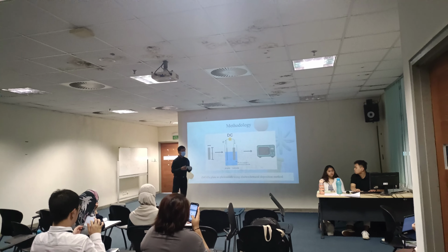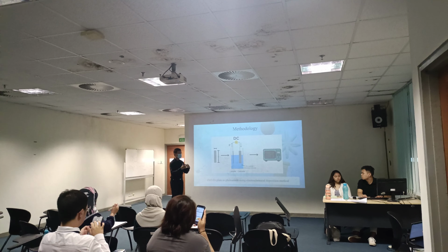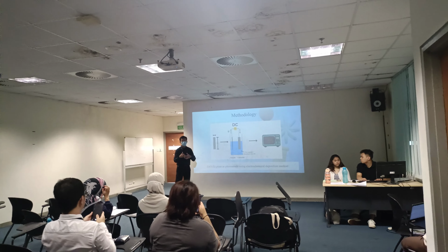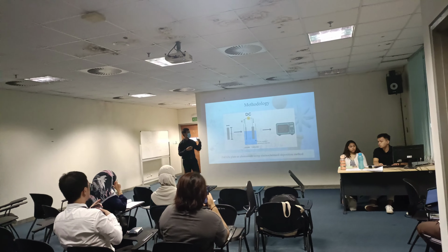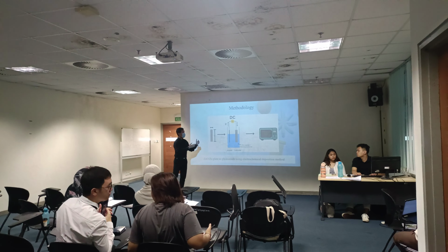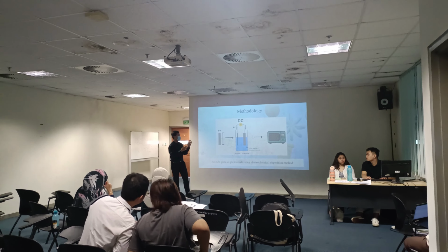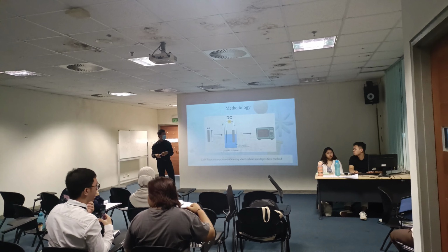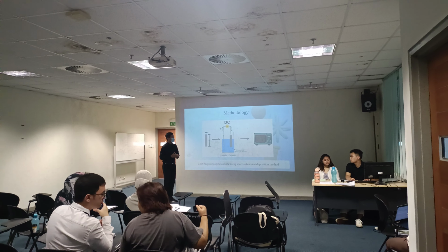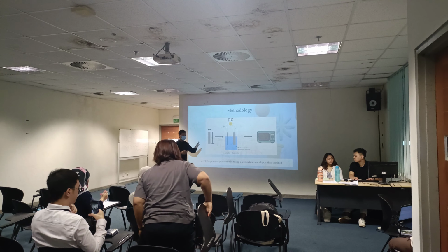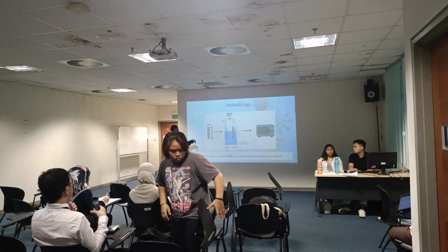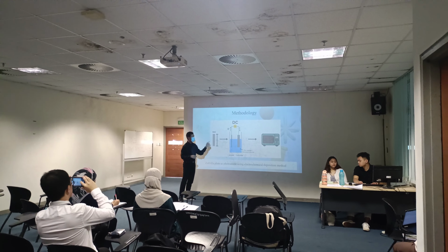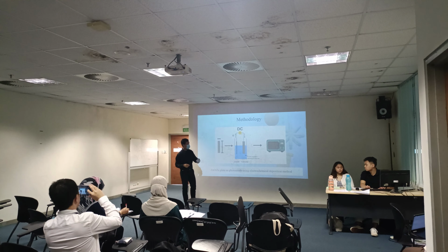For the methodology part, the zinc oxide/zinc photoanode was prepared by using the electrochemical deposition method, whereby the zinc foil will be cut into the desired dimension, and then it will be connected to the cathode side of the direct current, with a graphite plate at the anode side, and both will be submerged into a solution of 0.05 moles zinc acetate and 10% potassium chloride. After constant stirring for 5 minutes at 5 volts, the photoanode will be taken out and rinsed with distilled water, and then put into the oven to dry at 120 degrees Celsius for 24 hours.